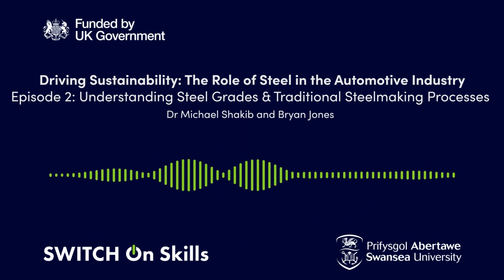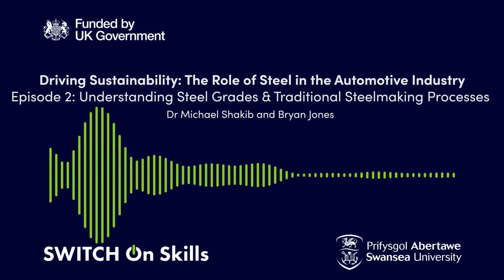So that's injected at high speed into the vessel. Silicon is the most reactive element, so that's reduced first, and then you reduce the carbon that's present. So you're reducing the amount of carbon present by a factor of 100. Wow. And then phosphorus is the last ingredient that's removed.